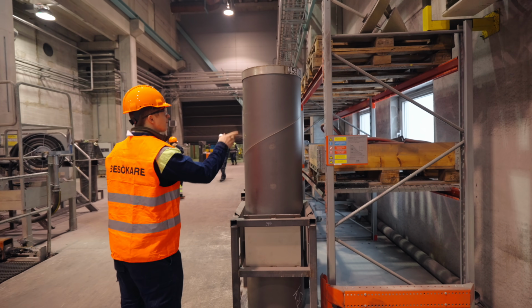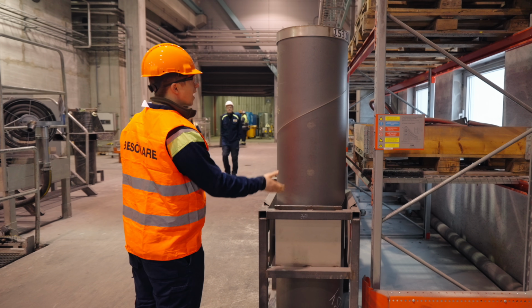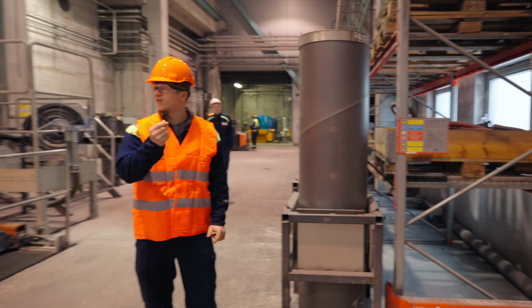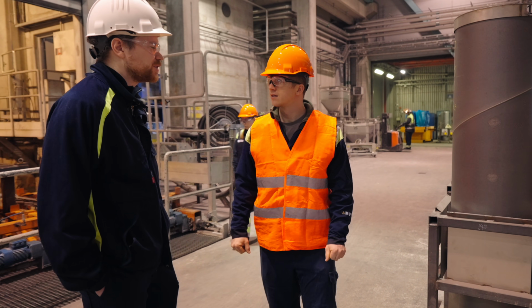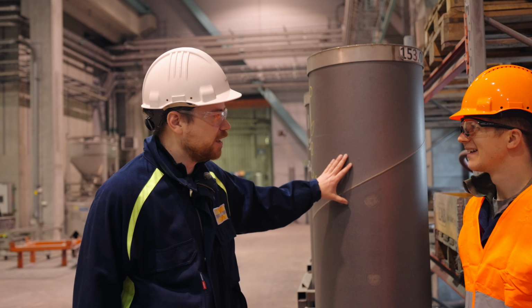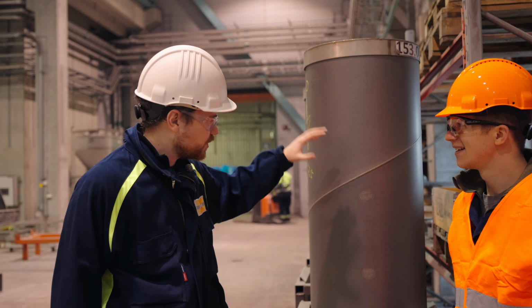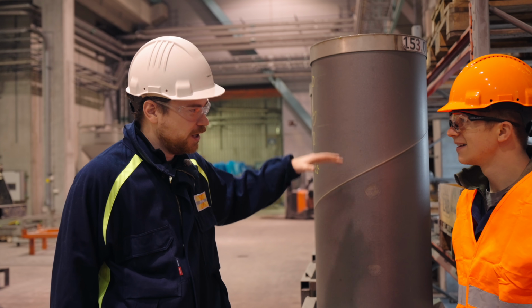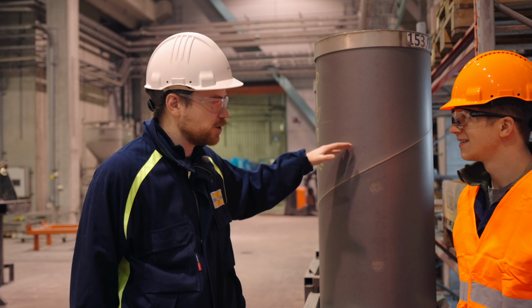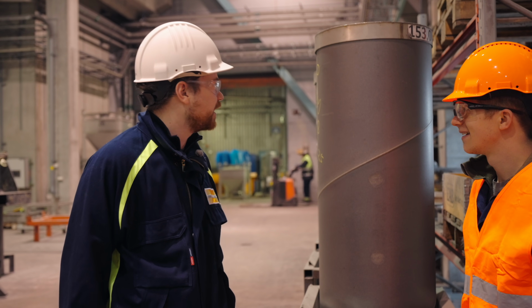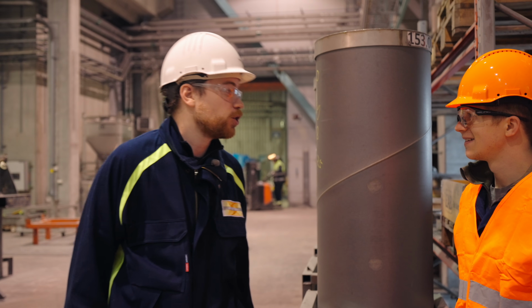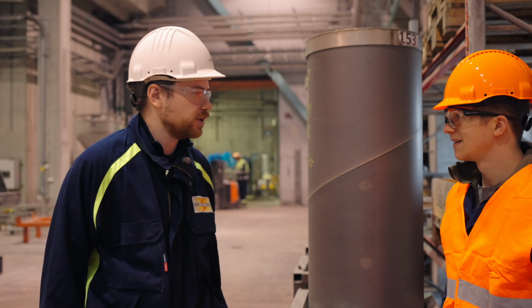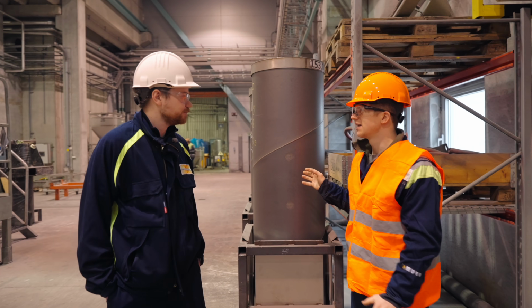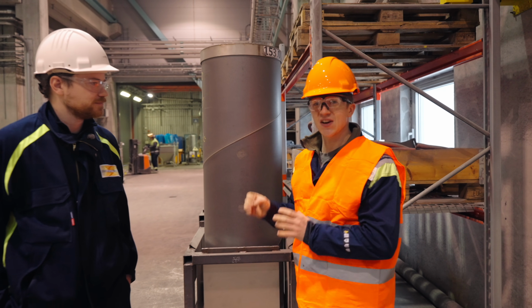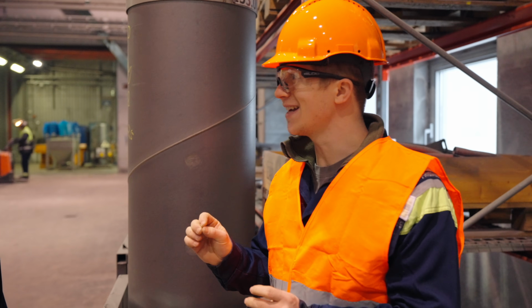Wow, and that is the famous capsule, spiral welded steel. How thick is the wall on that? 3 millimeters thick. Yeah. The hipping will be done inside this canister. So the canister is filled with powder, about 1.5 tons of powder. Then it's welded shut and compacted in a hot isostatic pressing unit. So this is functionally an identical process, but significantly more precise and clean.